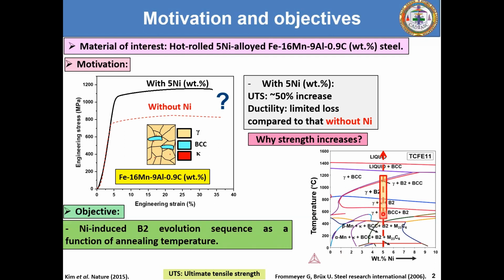And what we can clearly observe is that at a temperature of nearly around 500 to 600 degrees, we have the gamma plus the kappa plus BCC plus the B2 phases thermodynamically predicted to be stable. Then when we look at a temperature of nearly around 700 degrees, we see that we have the gamma plus the kappa plus the B2 phases stable here. Then at a higher annealing temperature of around 900 degrees, only the gamma and B2 phases are thermodynamically stable.